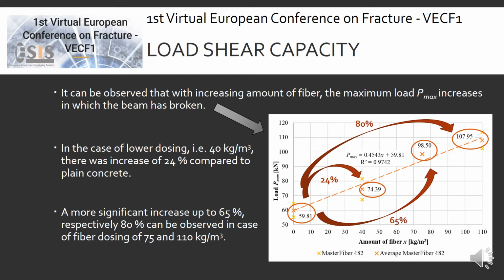In the case of lower dosing, that is 40 kg per cubic meter, there was an increase of 24% compared to plain concrete. A more significant increase, up to 65% and 80% respectively, can be observed in the case of fiber dosage of 75 and 110 kg per cubic meter.